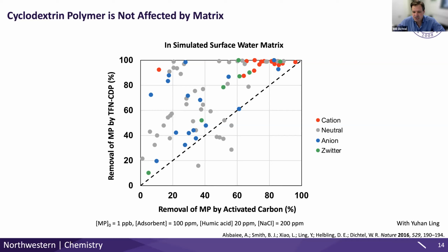And there's an additional aspect thrown into the mix here, and that is that we've included a little bit of a simulant for natural organic matter, so this humic acid, into our water. And the humic acid is known to foul activated carbon. And that's exactly what you see here. In the absence of humic acid, activated carbon can remove some of these pollutants even more effectively than our materials. But as soon as you start having more realistic amounts of these other natural organic matters, those will stick to the surfaces of activated carbon more strongly than these pollutants will.